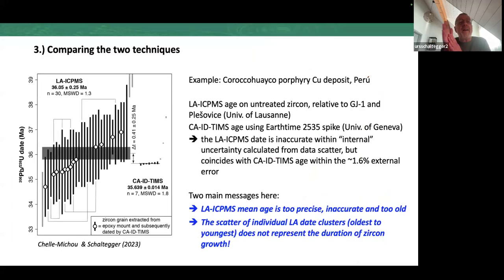Which now leads us to some case studies where we can compare the two techniques. So this is a porphyry copper deposit, a nice laser ablation cluster, weighted mean age. And then these zircons where we have these circles were plucked out of the epoxy and dated by chemical abrasion ID-TIMS dating. And what we now can see is that this cluster here, which is analytically, even statistically, significant, is inaccurate. It's too old because the chemical abrasion ID-TIMS date is younger.